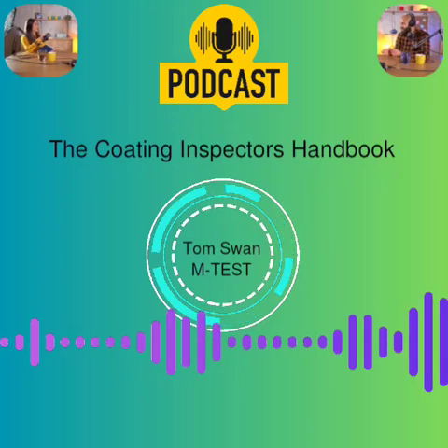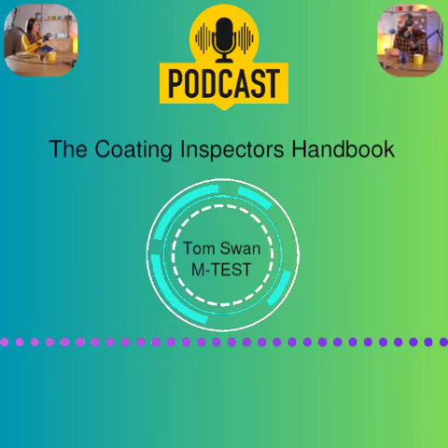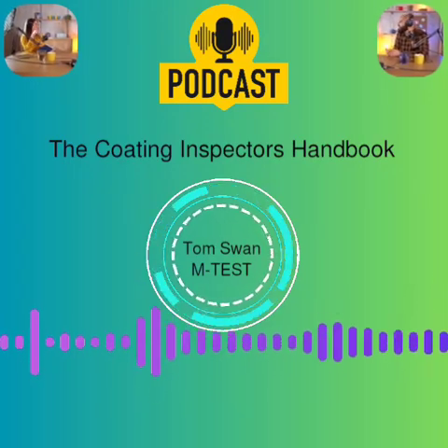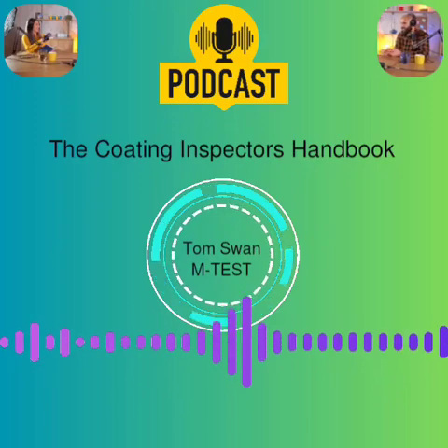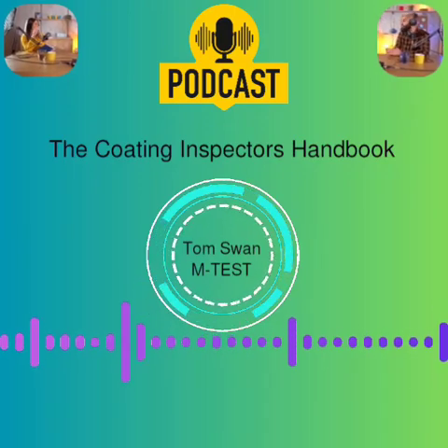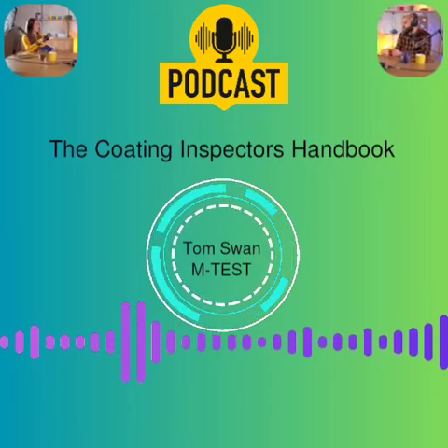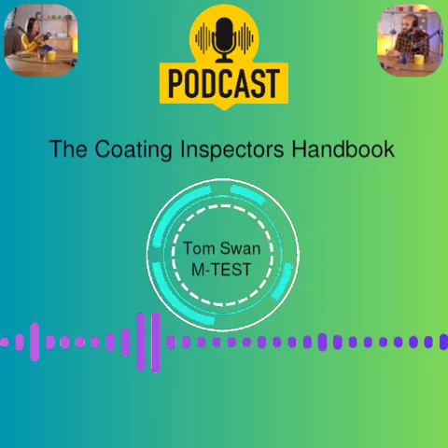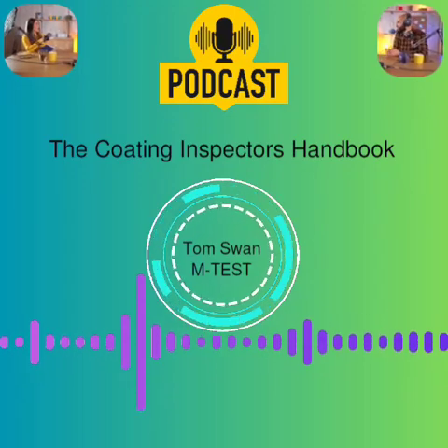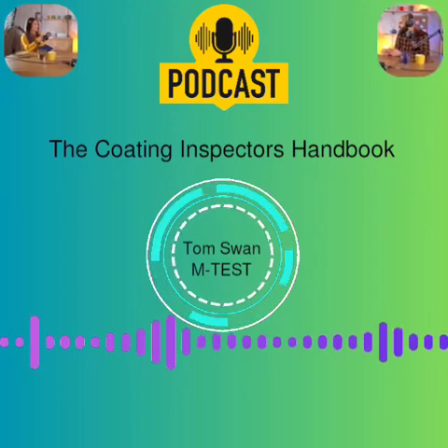You mentioned peak density. Yeah. Seems important, but maybe overlooked. It really is. Hugely important for the bond. You could have 2 surfaces with the same depth measurement, right? Okay. But one might have peaks far apart, low density. The other has peaks crammed together, high density. That high density surface gives way more points for the paint to grip.